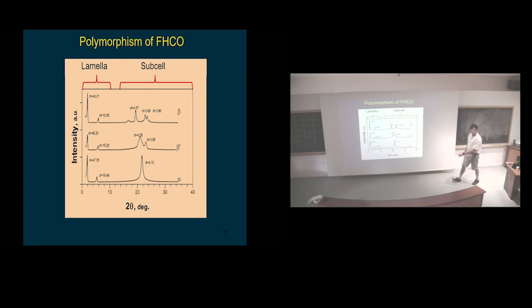And so this is a bit of a lecture, right? Somebody gives you this, and the fat maker goes, okay, at least hopefully you remember alpha, beta prime, beta at the end of all of this. So look at the hexagonal packing. The hexagonal is characterized by one characteristic reflection, as you will see in a second. And you get one massive peak at 4.1 angstroms. Show you where that comes from. The beta prime is characterized by two characteristic lengths.